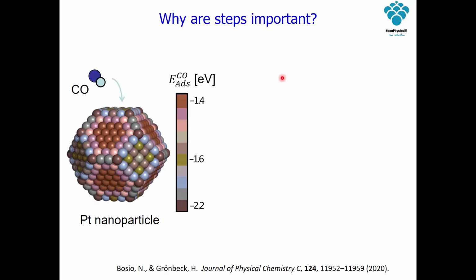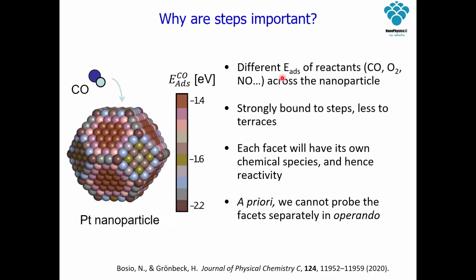So there is already some theory that will help us to do such things. For example, here we see a calculation from some years ago, where we show one nanoparticle, and the color scale here is the adsorption energy of the CO. Again, we have to have the CO stick to the surface, if not, we cannot do the reaction. And then you see on the color scale that we have a certain adsorption energy in the middle of the terraces, so minus 1.4.